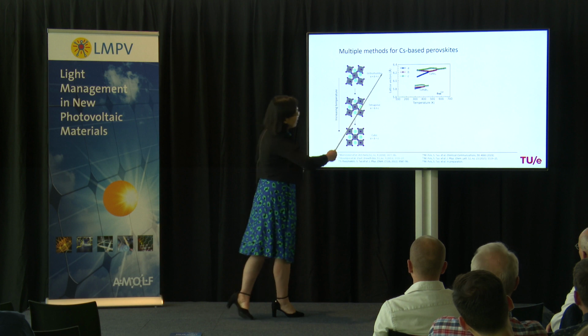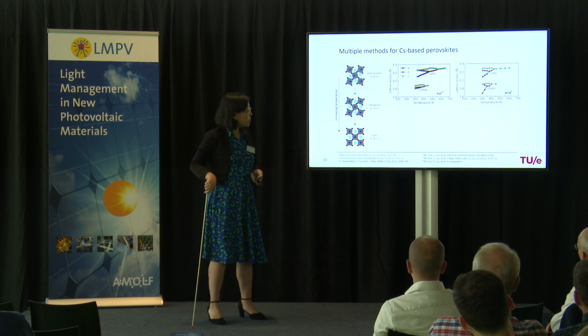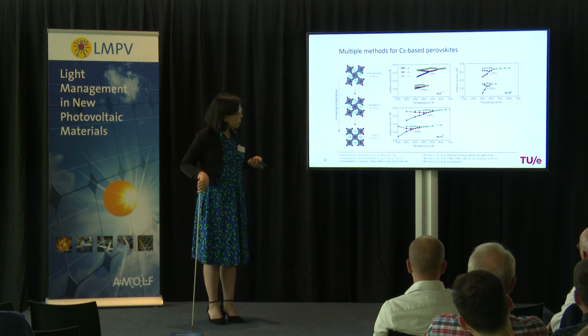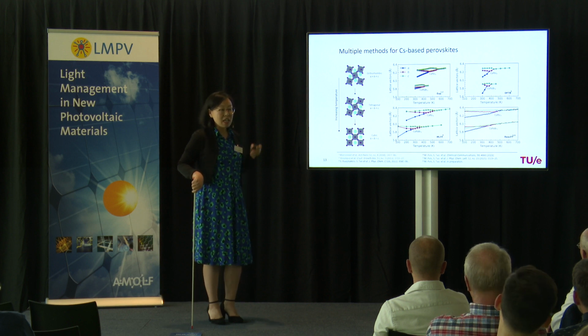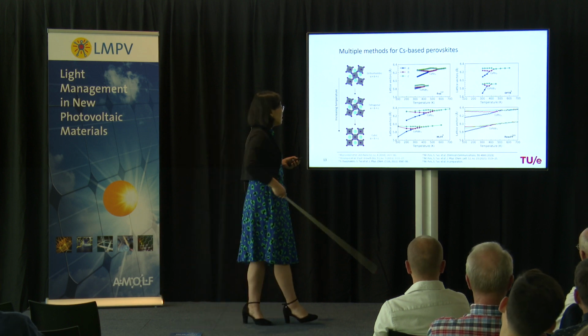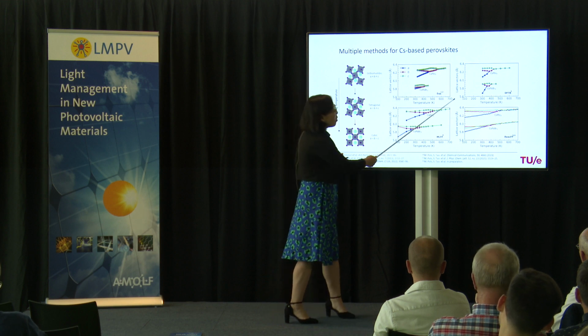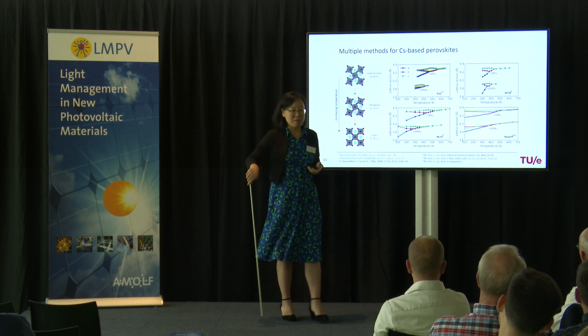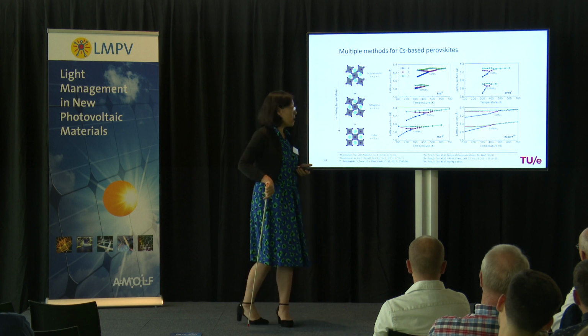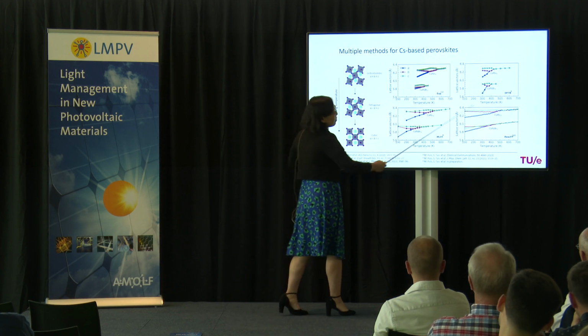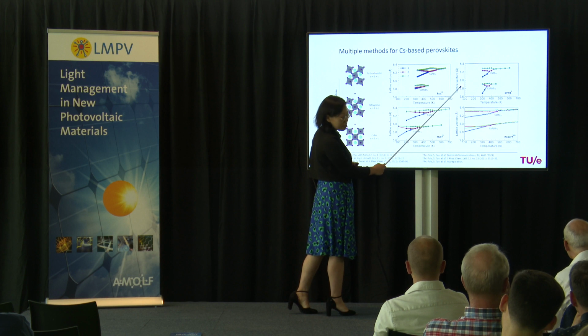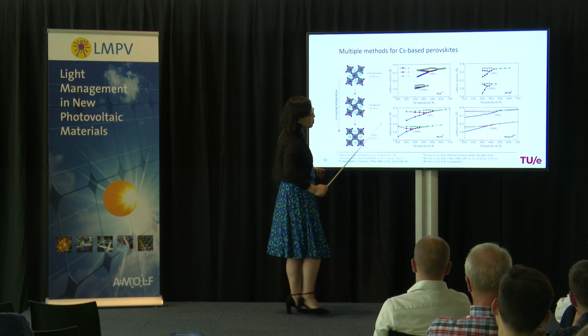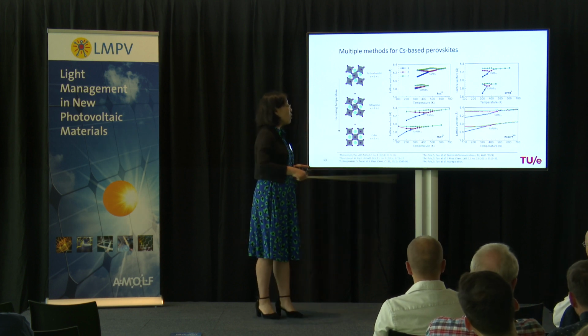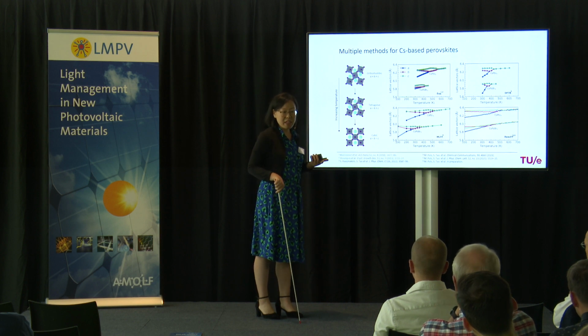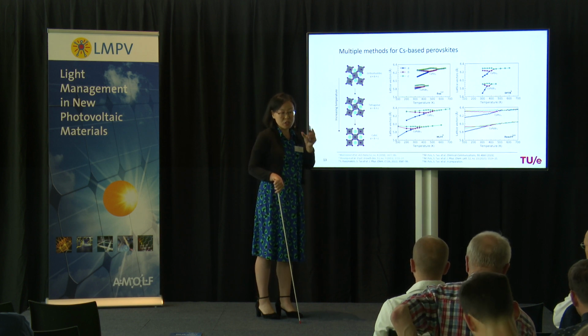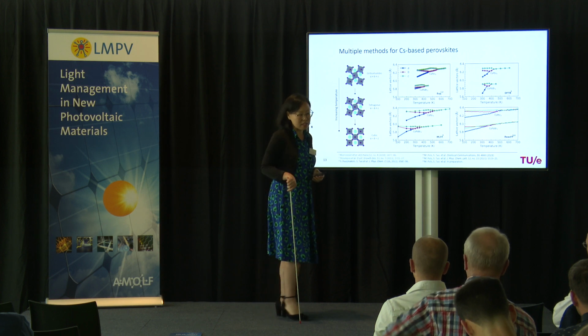This is experimental data, and as you can see, we explored 3 different methodologies. All of them qualitatively capture this dynamical property, and the more expensive methods are more accurate, but we cannot do a lot of simulation. This method describes electronic and ionic interaction at the same time. Machine learning is also very accurate, but here we only learn what we see. That means we can only use the force field to simulate the system we trained on.